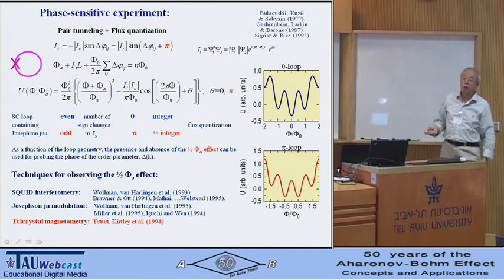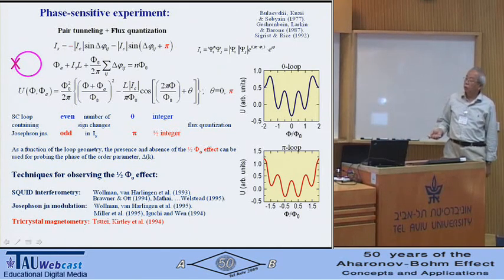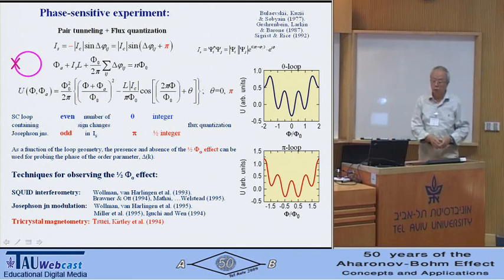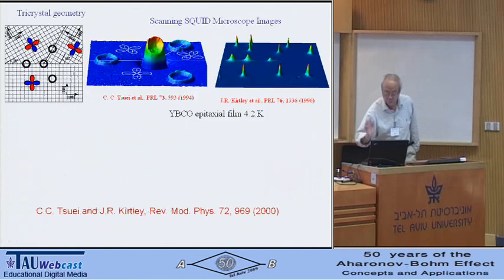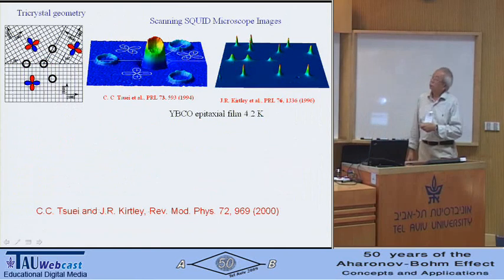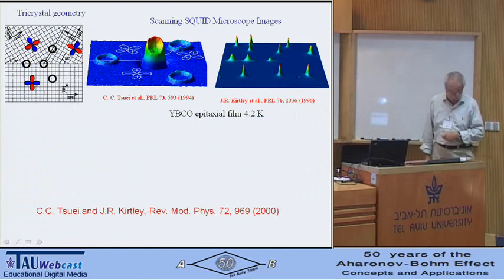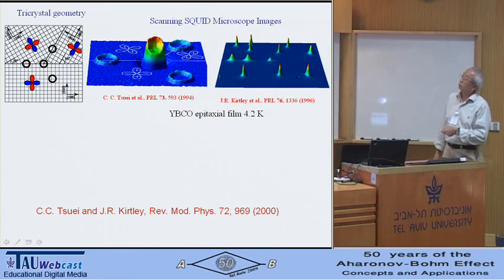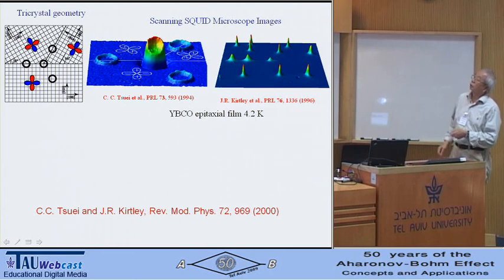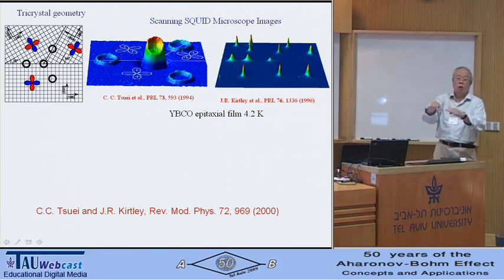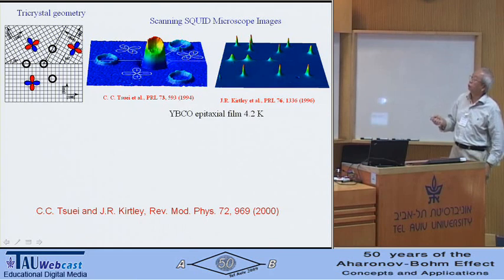In the past, several techniques were developed for observing the half-flux quantum effect. Let me concentrate on our own experiment, which we call the tricrystal experiment. I designed this experiment with a substrate consisting of 3 crystals specifically oriented such that if it's a D wave,